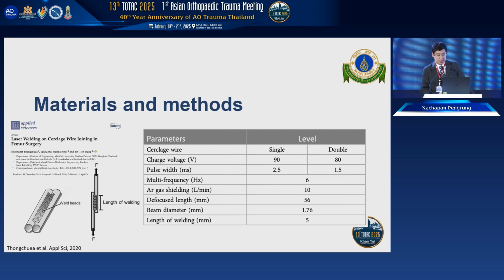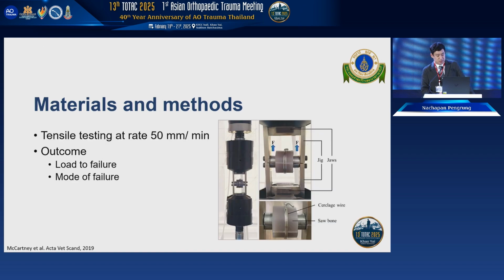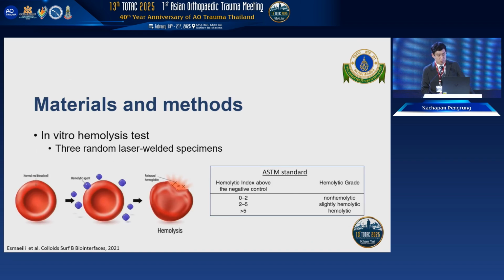This came from our previous study in collaboration with our engineering team, which tested the tensile traction of cerclage wire fusion. After setting up the biomechanical test as in the figure, we apply a tensile load to the specimen at a rate of 50 millimeters per minute. We measure the outcomes of load to failure and the mode of failure. For the in vitro hemolysis test, we randomly selected 3 specimens from the single and double wiring groups and tested according to the ASTM protocol. After that, we interpret the result. If the hemolysis is more than 5%, it is not acceptable for human use.